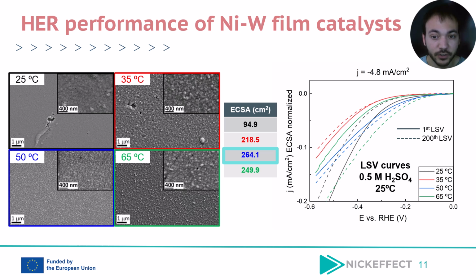After analyzing the potentials obtained from the linear sweep voltammetries, we could obtain 2 conclusions. The best performance was obtained at 50 degrees, and the samples at 25 and 65 have a lower resistance to the acidic media, since as we can see in the graph, there is a big variability between the first linear sweep voltammetry and the 200th.